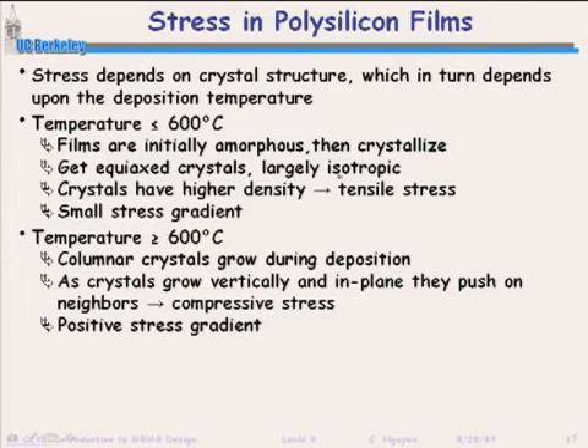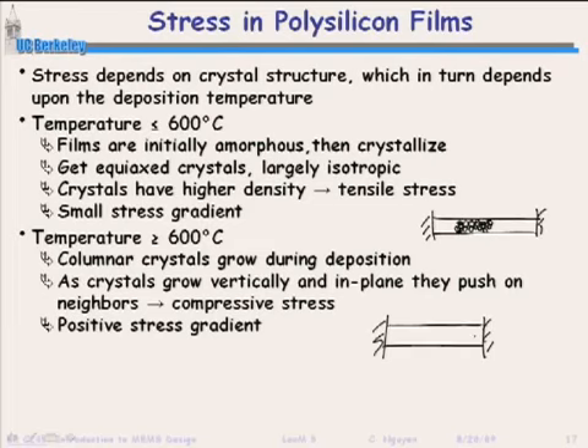So what do I mean by that? If this is the edge of, say, a beam that I have here, I have tiny little crystals like this, and they're packed very close together. Since they're packed close together, maybe they want to be smaller than the substrate around it. That's opposed to if you deposit at temperatures greater than 600 degrees. If I deposit at temperatures greater than 600 degrees, columnar crystals can grow during deposition. So what does that mean? That means the crystals are very large. So at low temperature, you get fine grain crystals. At high temperature, you get large grain, and columnar means they may even be like this.